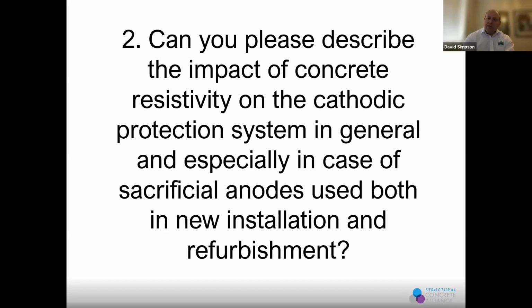But typically we're quite lucky, because where you have reduced resistivity, you have more water and more chloride, and reduced resistivity obviously relates to corrosion risk. So where we have high moisture and high chloride, you're going to have the highest ultimate corrosion risk on the structure. You can monitor resistivity over a structure. It's notoriously inaccurate in terms of what it is, but if you look at it for what it is and look at the delta, the difference between the values, it may give you an indication. As with any other technique to monitor corrosivity and risk of corrosion on structures, most of the time it's probability, and you have to combine various methods to be able to assess it properly. It is only a probability, but typically it's related to those changes in moisture and chloride, which gives us a good indication of risk.